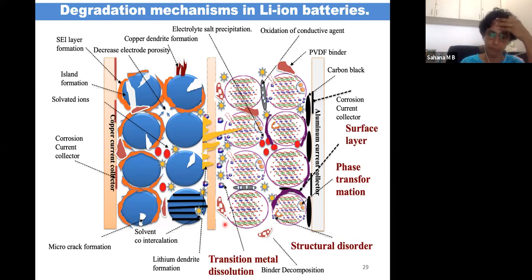The reason is that the electrolyte is LiPF6, that is, there is fluorine in it. As you know, if there is a small percentage of moisture in the electrolyte, which is extremely difficult to take away, even the best quality electrolyte will have around 15 ppm of moisture. So this LiPF6 reacts with the moisture and gives what is called HF. And HF can attack the surface of the active material, and the transition metal can dissolve in the electrolyte. So there are a large number of parameters that can spoil the cell.